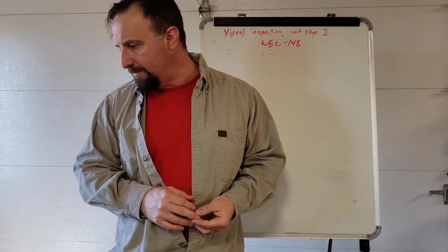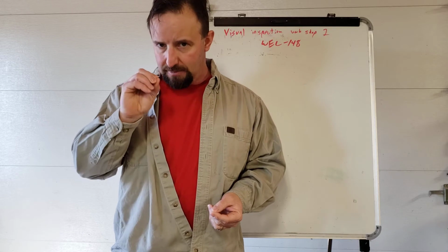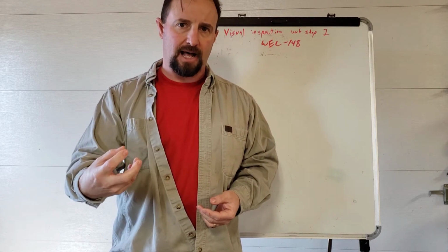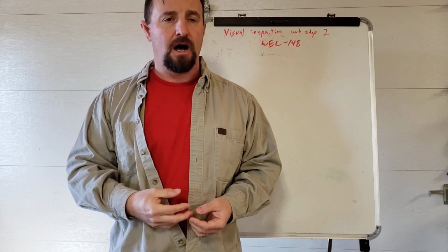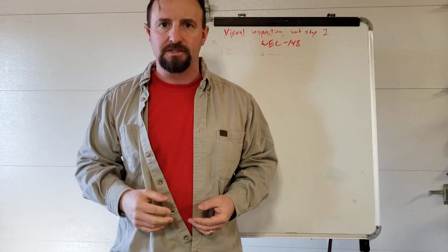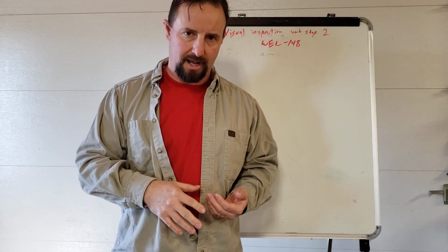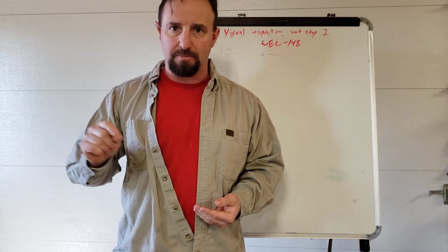And piping porosity. This is when you have welds that have itty bitty little pinholes that come up to the top, but the weld itself underneath it is basically nothing but holes. If we were to cut into this, that weld would basically be just cavernous underneath there. This is almost always an indication that you have some sort of root contamination. So the top of the weld looks okay, except for a couple little pinholes, but when you cut into it, it's just garbage, absolute garbage.